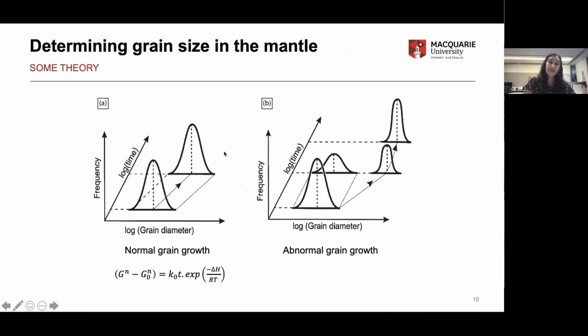So to ensure that I had normal grain growth occurring, because that's a process that we believe to be happening in the majority of the mantle, where we have low stress regimes. The story is different when we start thinking about deformation and uniaxial forces. But for the most part, we can consider normal grain growth to be occurring in the mantle. So to constrain the grain size and therefore the kinetics, we need to know the average grain size, and that should result in a log normal grain size distribution. From there, we can assess what the average grain size should be and apply it to the normal grain growth law. There's only one important parameter we need to remember today, and that's n, the grain growth exponent.